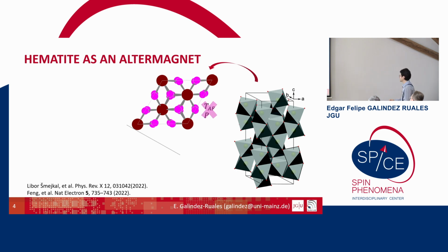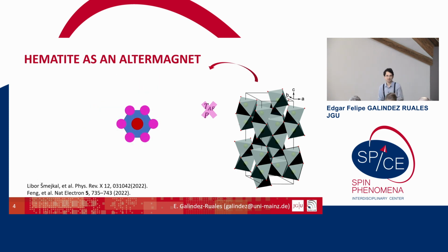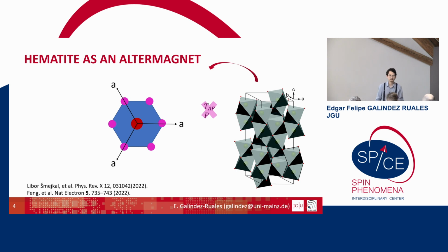So when you rotate the sample, it's important to notice that these oxygen atoms are in non-centrosymmetric positions. These oxygen atoms are responsible for breaking the inversion and PT symmetries. When we rotate the sample to better see the hexagonal structure I was talking about, we have something like this. I simplified the structure because there were too many atoms, and then we have a nice hexagonal structure, and I will define my crystal lattice in this way.